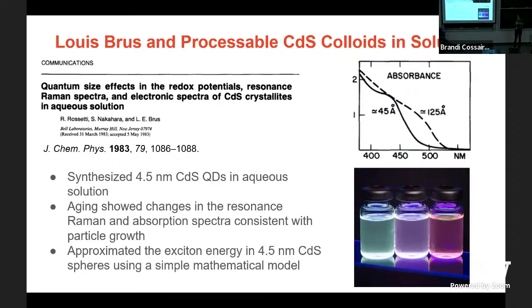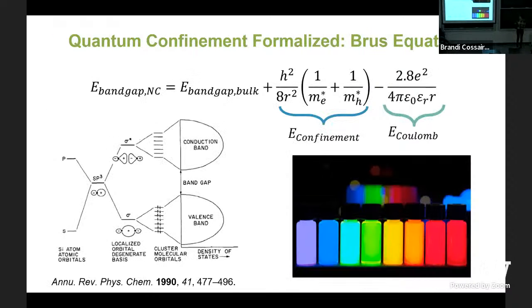Brus first synthesized cadmium sulfide nanocrystals in solution and saw a similar size effect to Ekimov in his frozen glass quantum dots. He found that as the size increases, you see a redshift in the absorption. But Brus went a step further than Ekimov and didn't just say, quantum confinement, we're good. He actually formalized the mathematical equation to tell us what we can expect to see based on the fundamental constants of the material. And so the Brus equation is the formalized equation that tells us what our band gap should be given the fundamental constants of the material, and most importantly, the radius of your quantum dot. And it's this energy of confinement term that causes the increased band gap and is the quantum confinement that's causing these particles to have a higher band gap when they're a smaller radius.